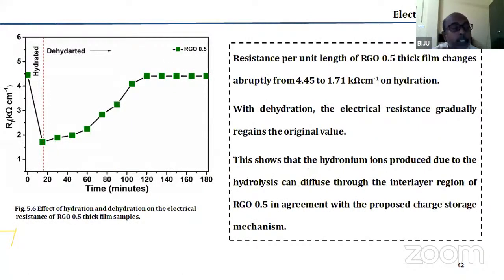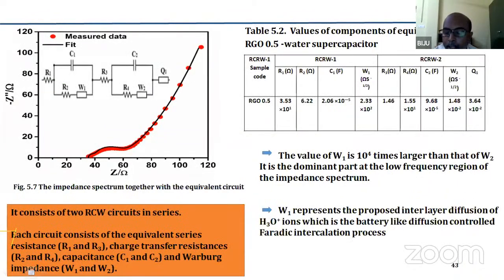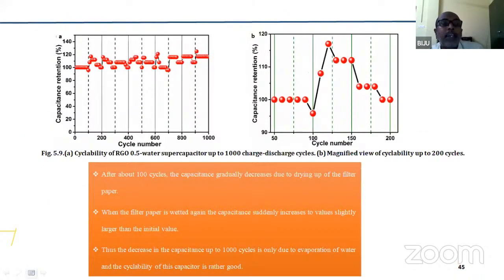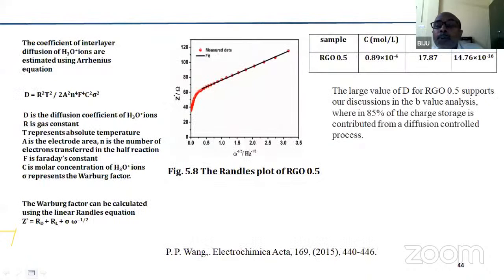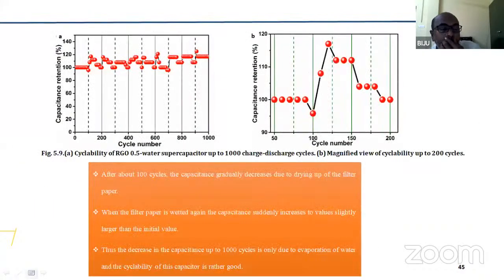Again, before that, we also did one more experiment. When this material was dry, you have a particular resistance value. But if you hydrate it, if you add some water, the resistance suddenly decreased many-fold. And then if the material is allowed to dry, it regained the original resistance value. So this also supported our hypothesis that when our RGO material is in contact with water, these H3O plus ions are produced. Again, let's skip this, and we actually measured the diffusion coefficient also, and the diffusion coefficient had a considerable value. Now, when this supercapacitor was charged again and again, we found that after about 100 cycles, the value of the capacitance decreased.